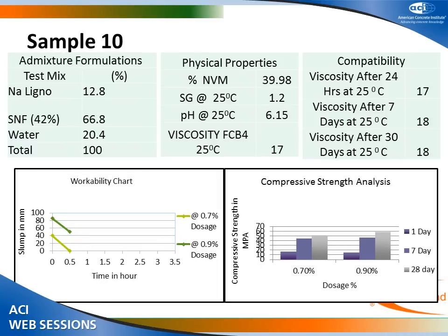For the second mix, almost the same. There is no change in the slump retention pattern, and compressive strength-wise it was less than the polycarboxylate, but basically I think the 0.9% dosage achieved something more than the 0.7% dosage, which was a bit surprising to us.